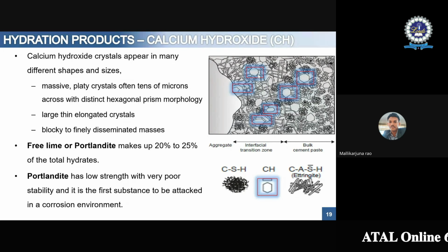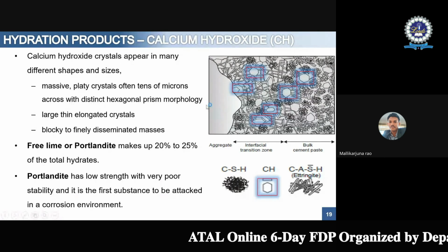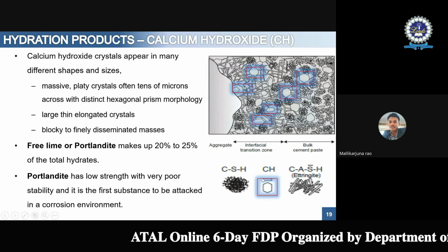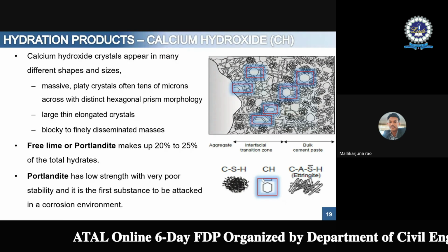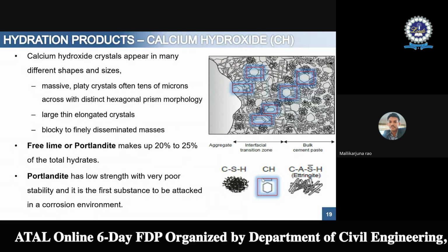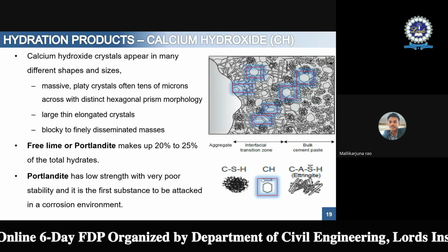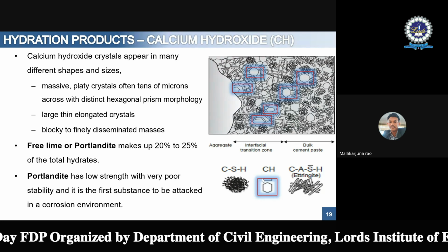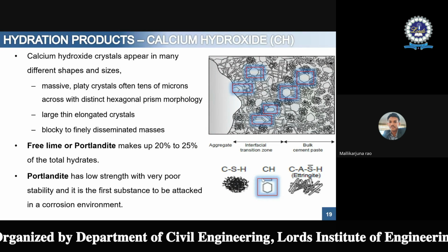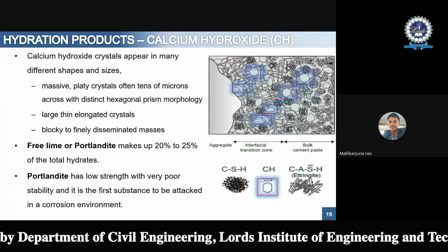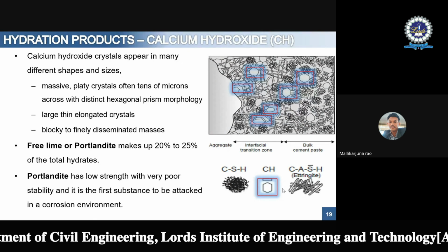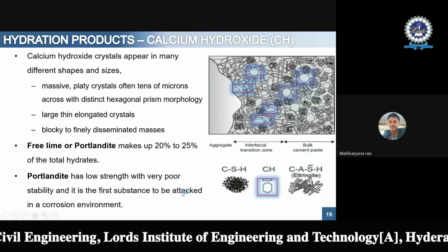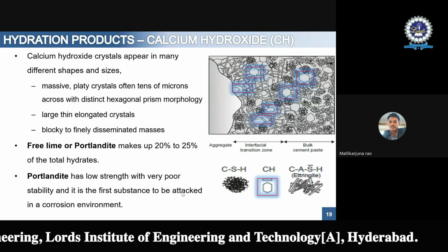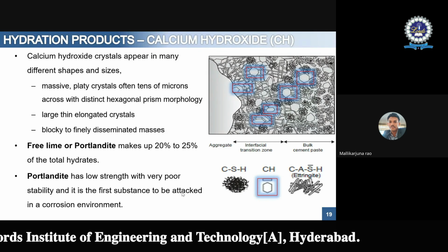The calcium hydroxide crystals you can identify whenever you go for the microstructure aspect, where we have plate-like crystals, and their size is also very small, in microns. This material is going to react with sulfates, chlorides, carbonates, and it is going to reduce the strength of the concrete. So the more calcium hydroxide you reduce, the more the gel or pore formation becomes very dense, and it is going to contribute a good amount of strength. If you consider your free lime or your portlandite, approximately 20 to 25% of the total hydration, there is a chance for free lime to be present.